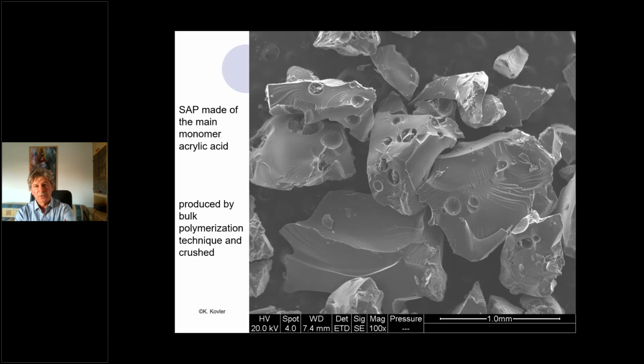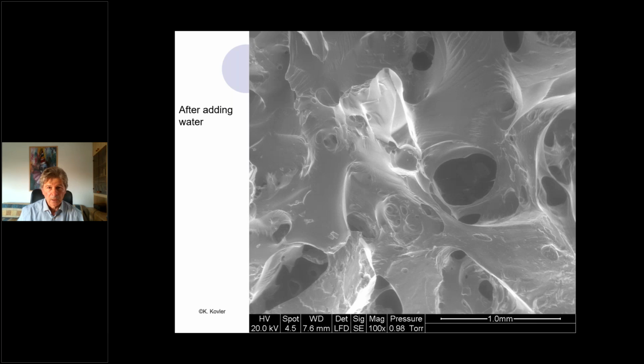Another kind of superabsorbent polymer, you can see another shape of the particles. It's not a spherical one, but crushed angular particles. This is an example of superabsorbent polymer made of the main monomer acrylic acid. This is produced by bulk polymerization technique and crushed. So you can see how the particles look before hydration, before absorbing water. And this is what we have after adding water. So the volume expands.